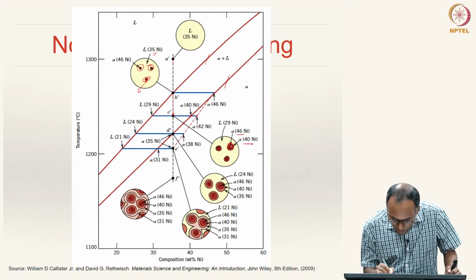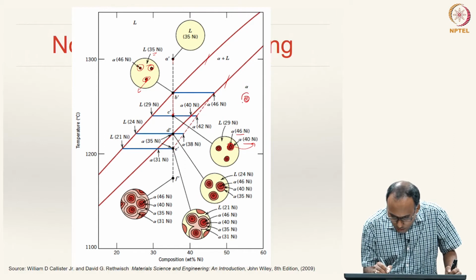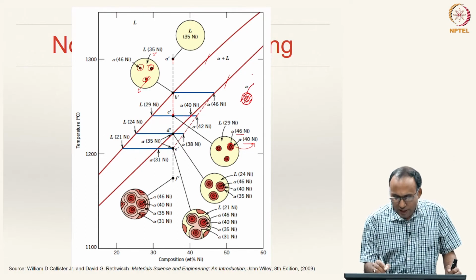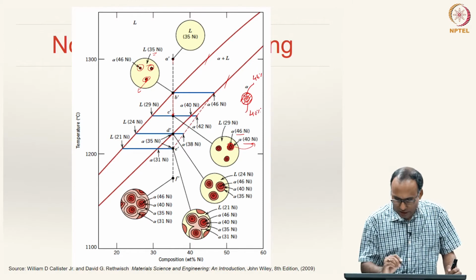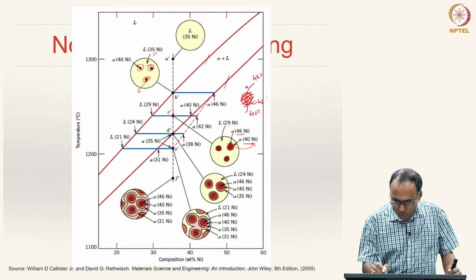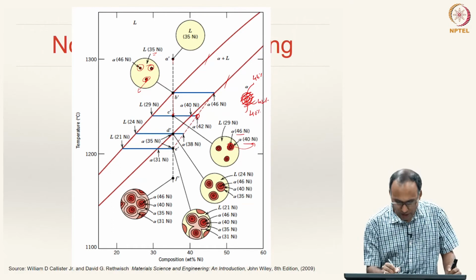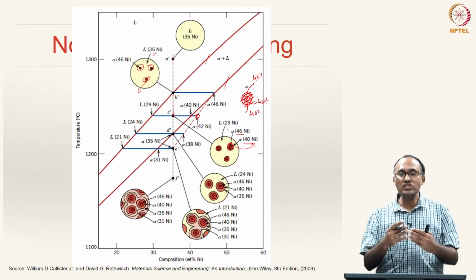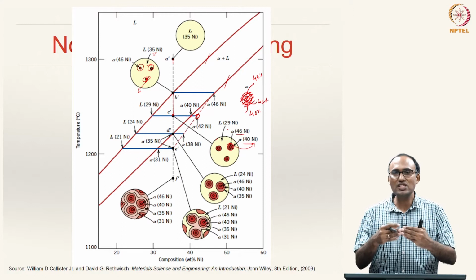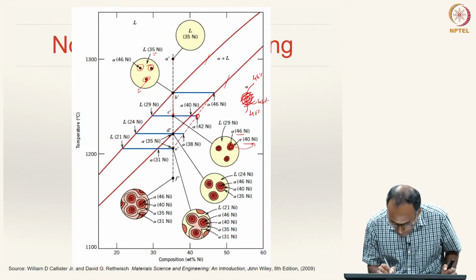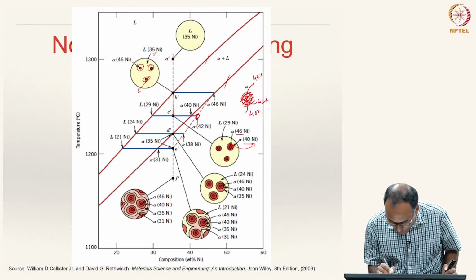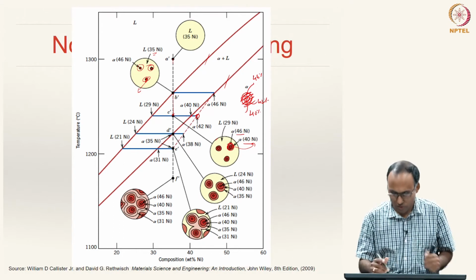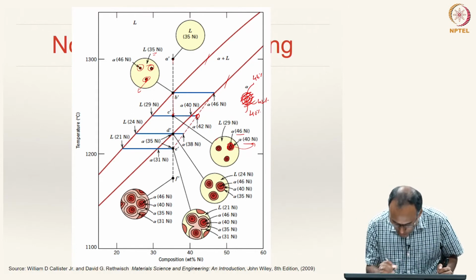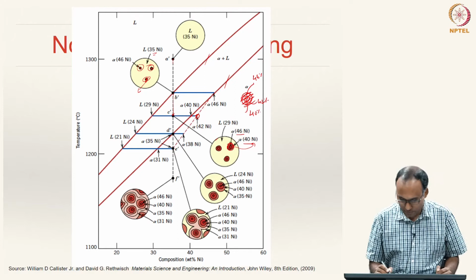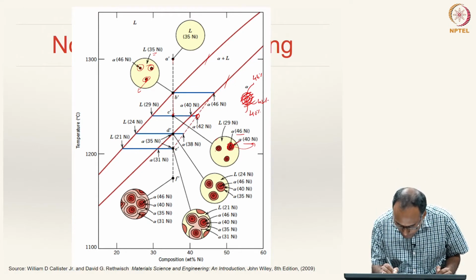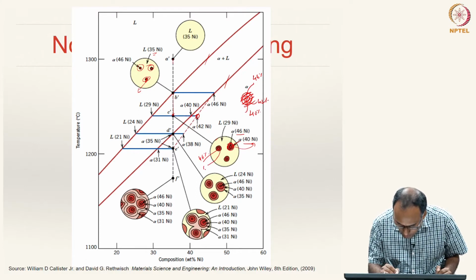If you take, so that means if you have this solid, this part has 46% nickel and this part has 40% nickel. On an average, this entire solid has 42% nickel, which is consistent with this. So, on an average you will have 42% nickel, but this 42% nickel composition is not uniform, right. This is not a uniform phase, it is a non-homogeneous phase. Sorry, I have done it wrong: at the center you still have 46% and the outer phase you will have 40% nickel, right. Here it is shown the other way, but it should have been 46% at the center and the outer phase 40%, something like that.